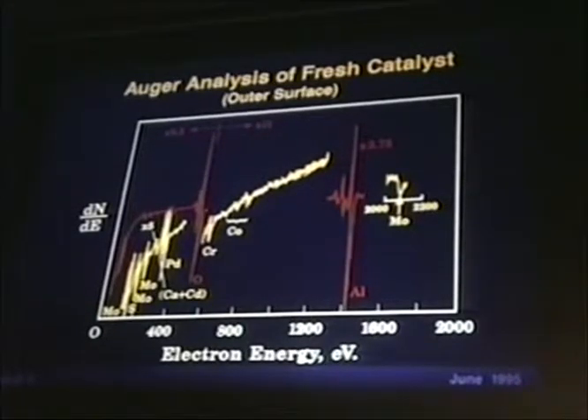The Auger analysis shown here of the fresh catalyst, you can see there are palladium peaks along with the cobalt, moly, and a small amount of sulfur and chromium along with it, other impurity elements. Now to the next one.